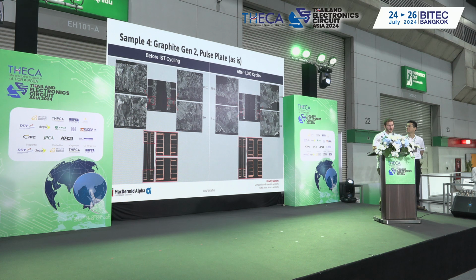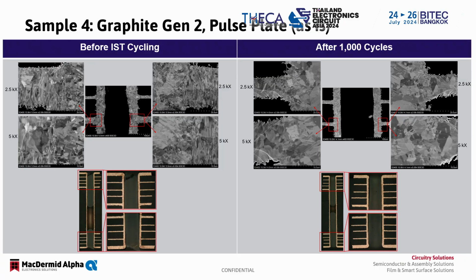We took the coupons, and to verify the performance was good, we also did cross-section analysis, which you can see from each condition, and then we did SEMs of before and after IST cycling to see the difference in grain structure and reliability at the joints. You can see here the grain structure points. This example here is for the graphite Gen 2 and pulse plating. We did it for all 4 conditions. We didn't see any microvoids. We didn't see any common concerns of reliability or failure points or soon-to-be induced failure points. So we felt the reliability was consistent with the results and showed no degradation in the performance.